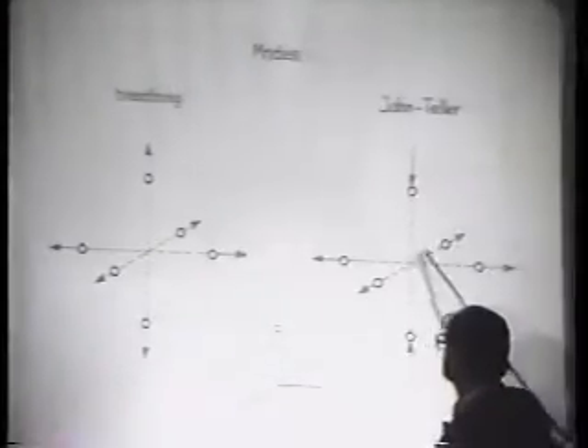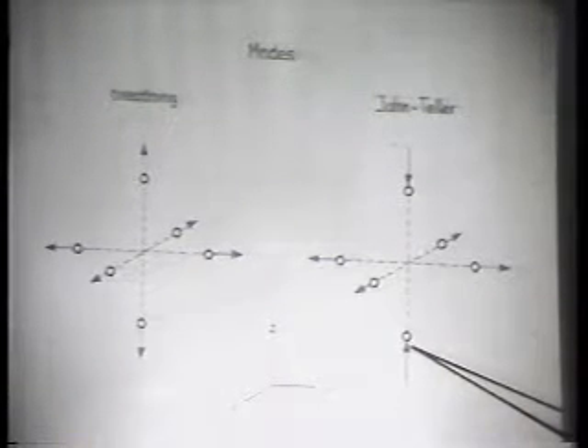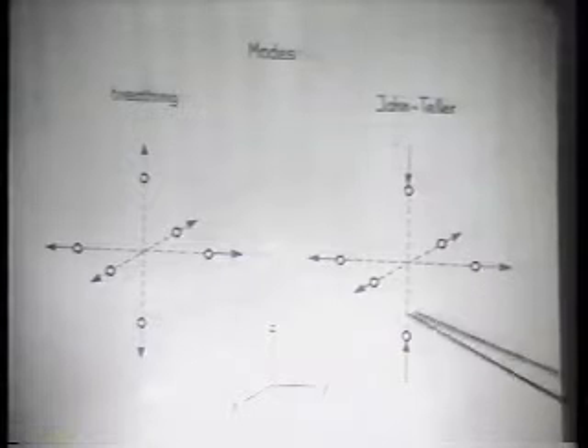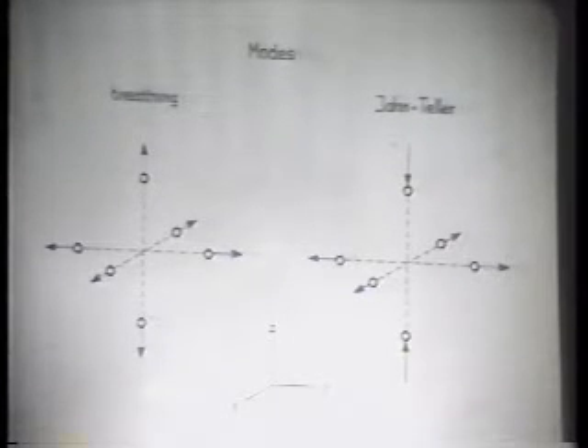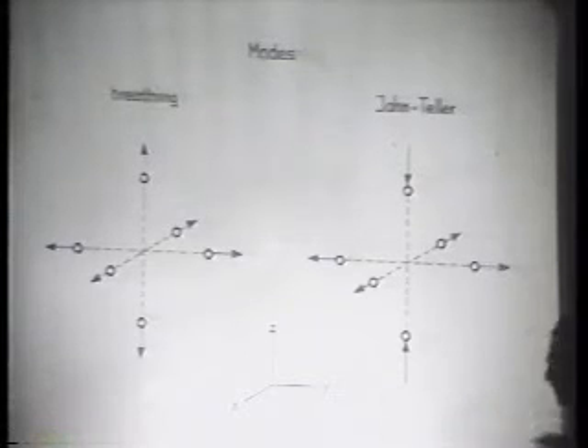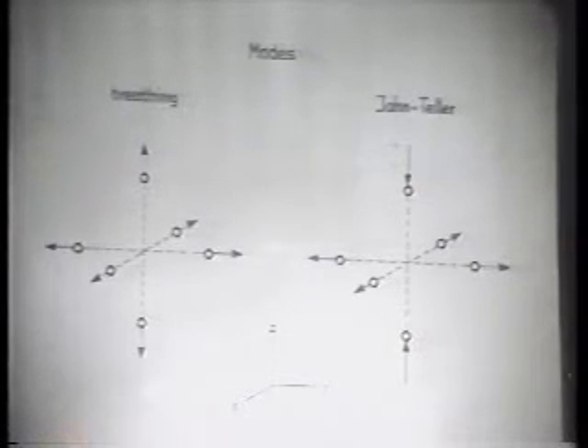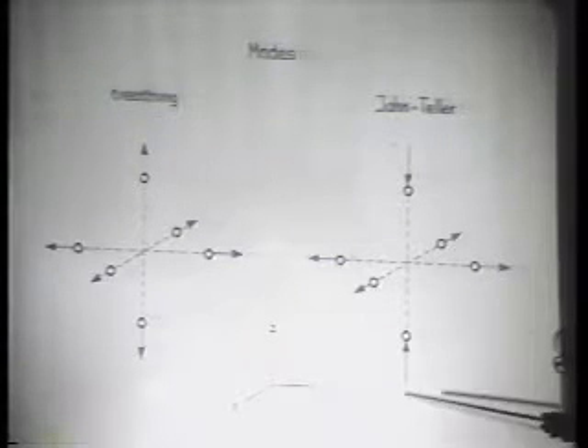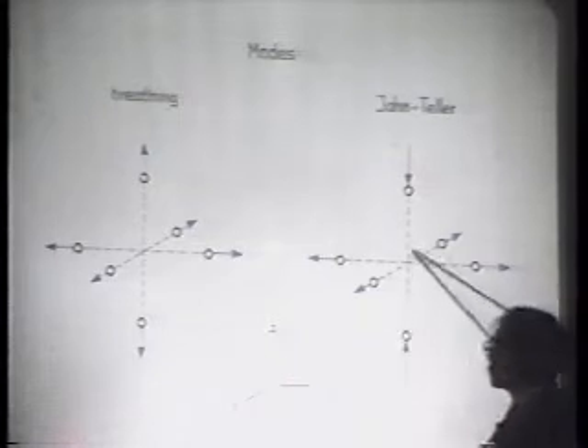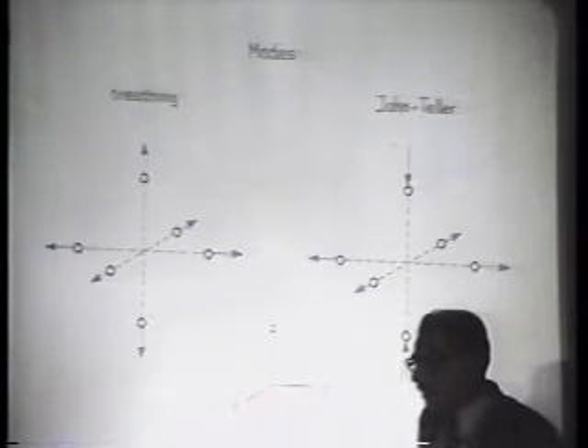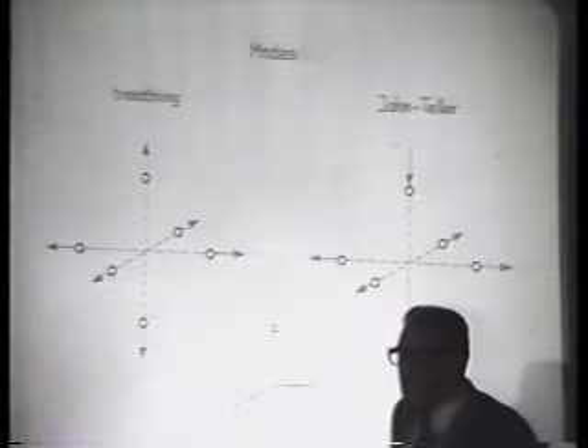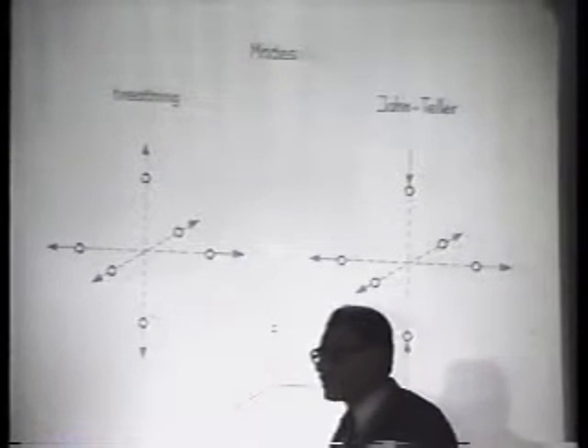On the other hand, here is the Jahn-Teller mode. You cannot distinguish in the xy plane the motion of the oxygens between the Jahn-Teller and the breathing mode. It's only the out-of-plane motion of the oxygens which is different. Namely here, the red arrows show 180 degrees out of phase. And it's not so much a matter of the amplitude, but of the phase. And to my understanding, there have not been experiments till now to distinguish between these two modes. This mode here preserves the volume of your octahedron, and this may be important because the copper ions, in general, as far as I know, do not disproportionate.